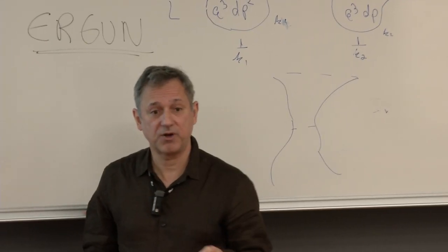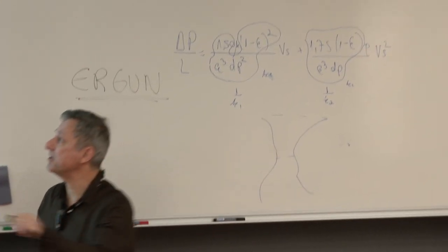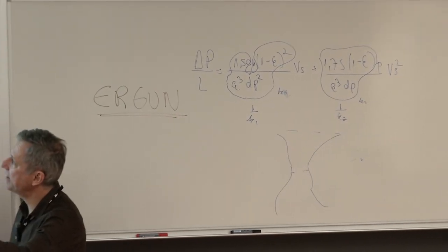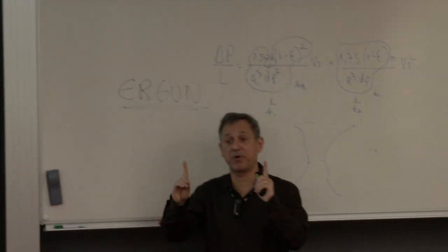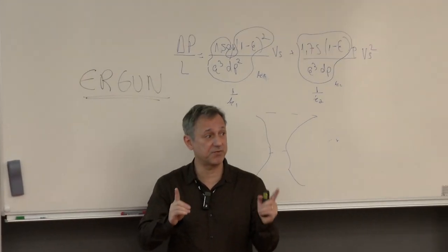This equation was prepared using a range here. But the equation today, we see that the equation is wrong. Because if you take this equation, you take this like a straight line here and you go through here. That's my paper. I'm not complaining about Ergun, but showing that Ergun is a very limited equation to predict the permeability of the material.